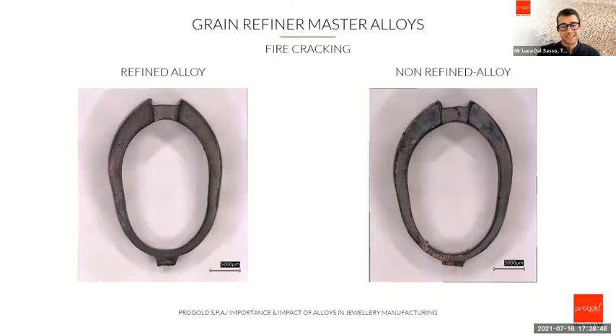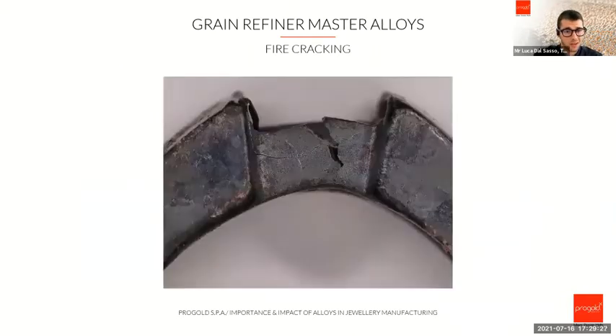There's no way to escape this test, because once you have an alloy which is not well refined, the microstructure does not have the small size of the grains. This is a defect in a ring like this, which is empty on the hidden part under the crack. This is a geometry that is wanted by us to show the firecracking. So this thermomechanical stress is a really huge problem in the 18 karat red gold, and you can see it also in the next slide with the zoom. Can you see how huge this crack is?